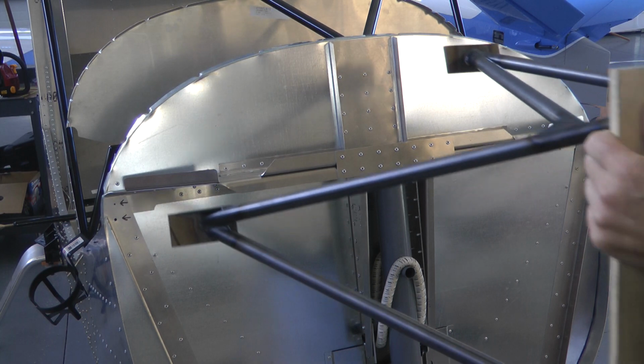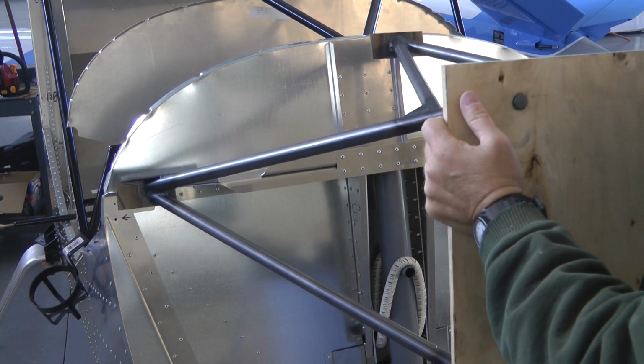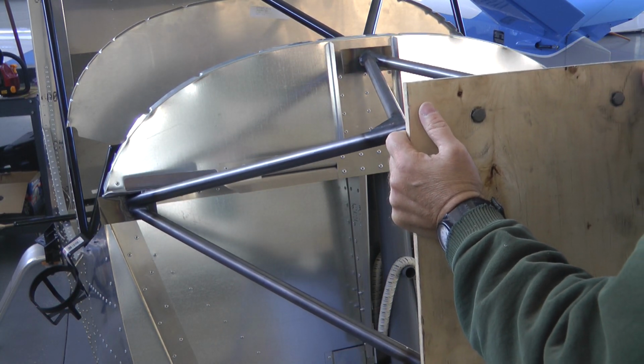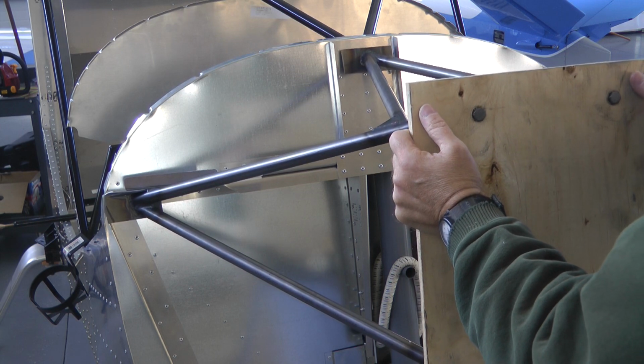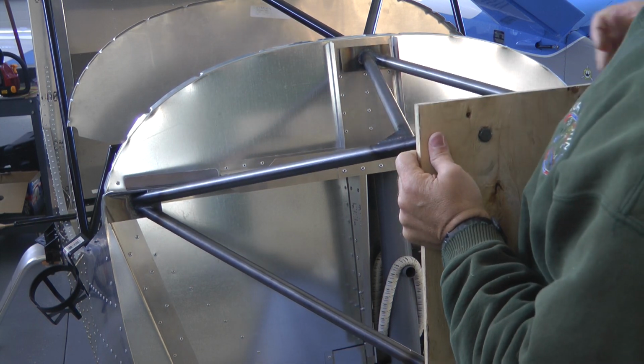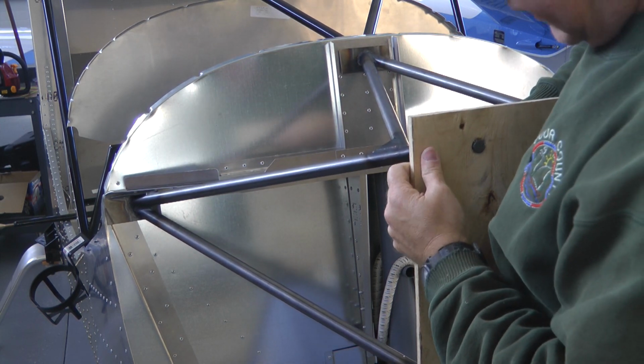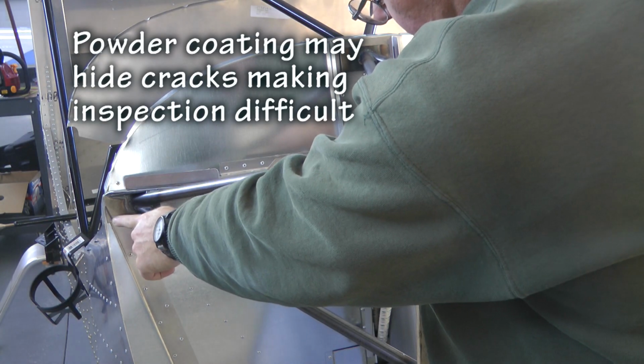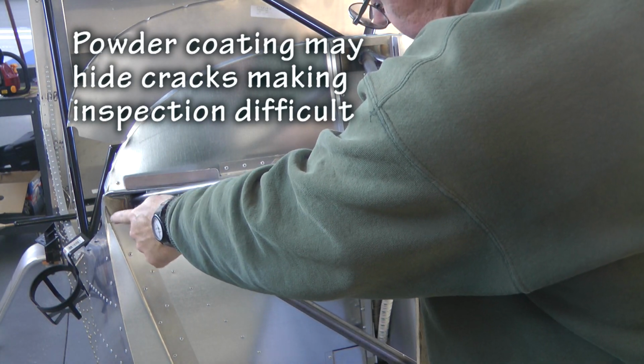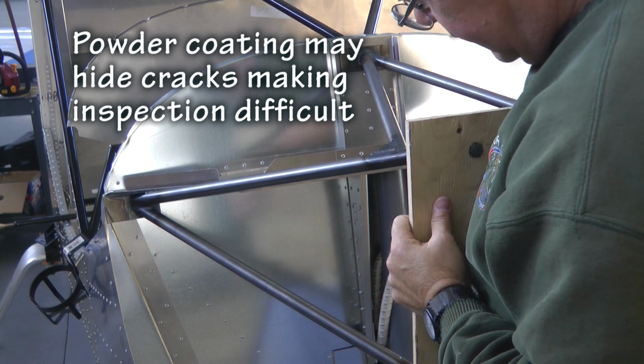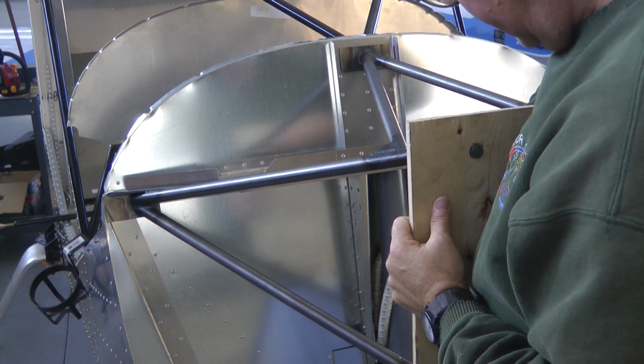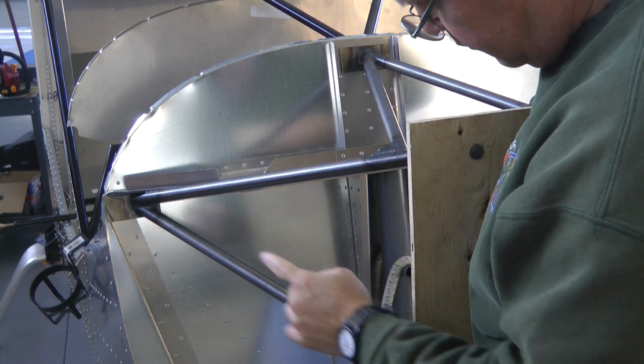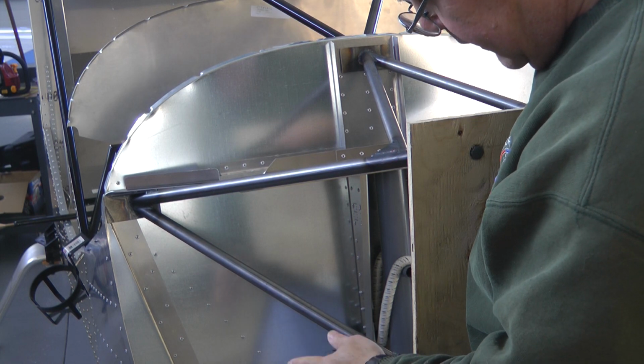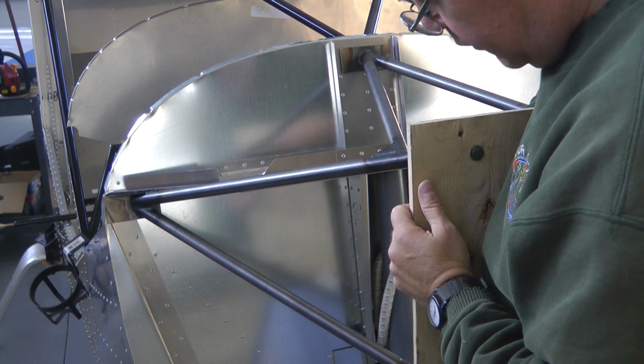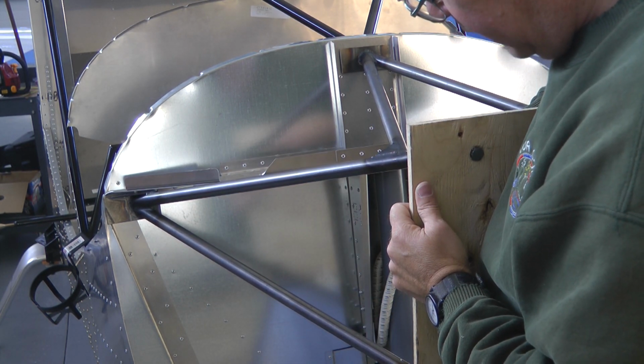One of the metal components of your home-built aircraft that we do not recommend powder coating is the engine mount. And that is because the powder coating does a wonderful job of hiding flaws and imperfections. In particular, any cracks that may develop at the welds may be hidden by powder coating. So it is actually better to paint these rather than have them powder coated.